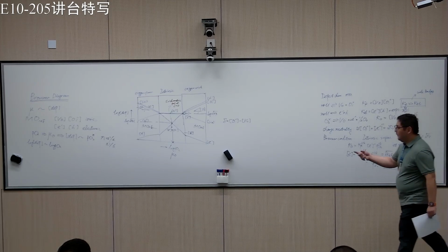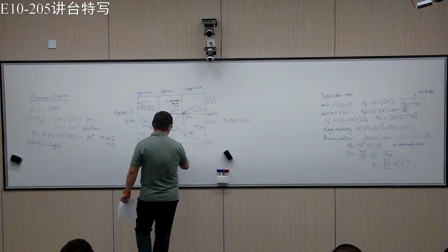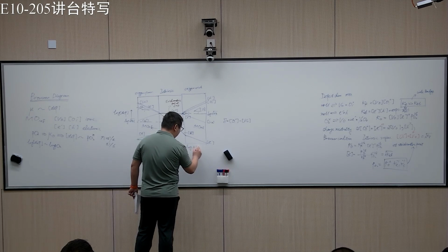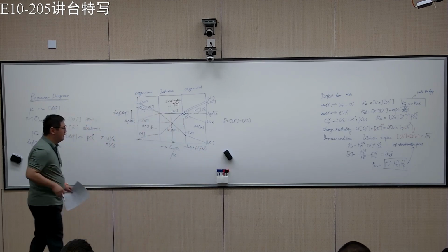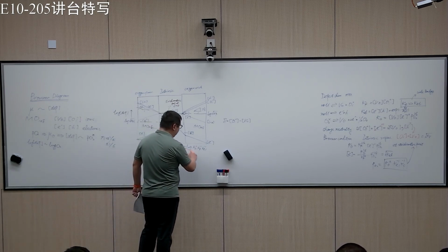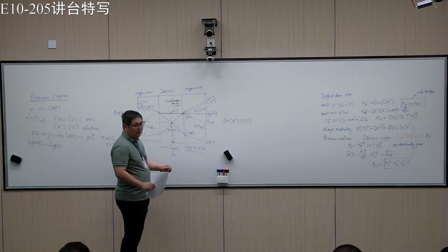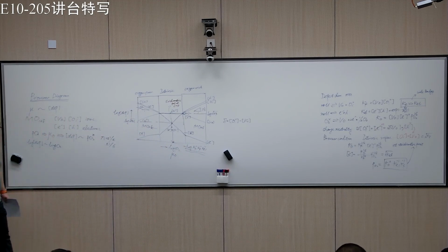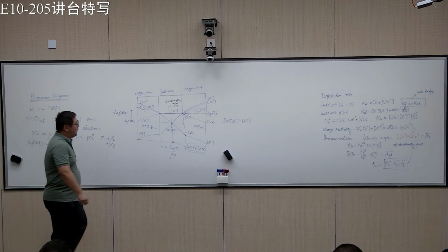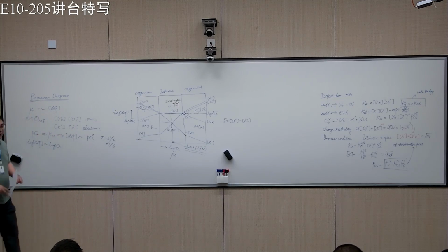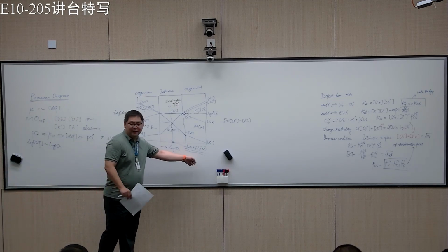So basically you can plug in here, so this point should be less than KO squared KF minus 1, KEL to the power of minus 1. As you can imagine, if you change your material system, essentially what you are changing is this constant. These values are going to change. So it's very important to know where you are depending on your material system. You will know that once you can measure all these constants.